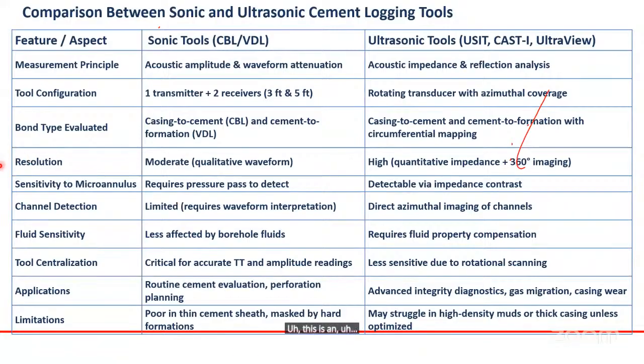This is a comparison between sonic and ultrasonic cement logging. Very quickly, measured principle: acoustic amplitude and waveform, acoustic impedance and reflection analysis. Okay, two configurations: one transmitter, two receivers at 5 and 3 feet, rotating transducer with azimuthal coverage. Bond type evaluation: casing to cement CBL and cement to formation VDL; casing to cement and cement to formation with circumferential mapping. Resolution moderate. High, quantitative impedance at 360. So the ultrasonic is higher. Sensitive to microannulus.